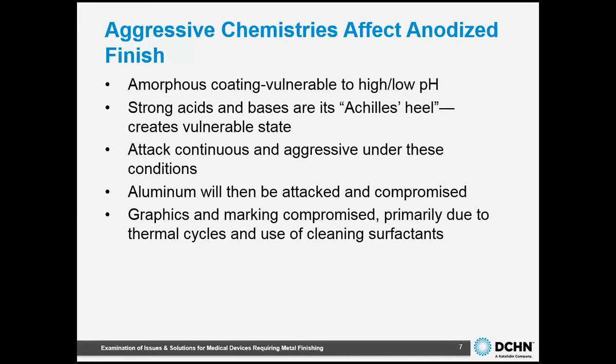Now, while anodized has some great characteristics, its Achilles heel has always been its inability to resist very high and very low pH chemical attack. You see, once the anodized film is compromised by these chemistries, the attack on the coating is rapid and aggressive. And the resultant degradation not only affects the coating, but also the graphics and markings that are on the device. I will discuss more about that in a few minutes.